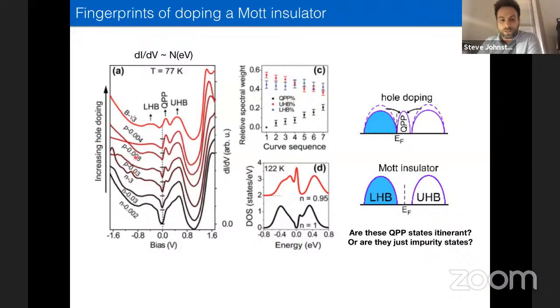And now as I increase the doping level of the substrate, what's seen is that there's a peak that begins to emerge inside the gap, and it looks like the formation of one of these quasiparticle bands. And depending on how lovingly you look at this, you can argue that maybe some of that spectral weight is coming out of these upper and lower Hubbard bands. So here, Fang Fei actually tried to be a little bit more quantitative. He was fitting these lower and upper Hubbard bands and quasiparticle peaks with Gaussians to try to measure spectral weight. And what he found is that with increasing doping, the quasiparticle peak looked like it increased linearly. And this came at the expense of the upper Hubbard band, and the lower Hubbard band was a little bit more difficult to see as a function of doping.